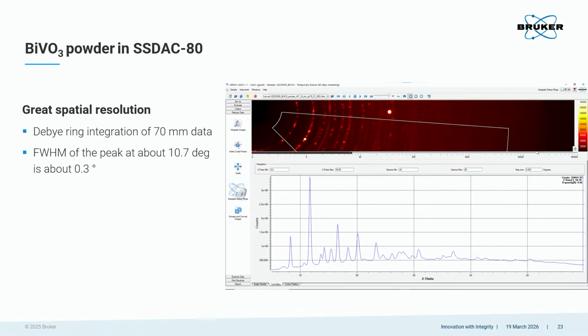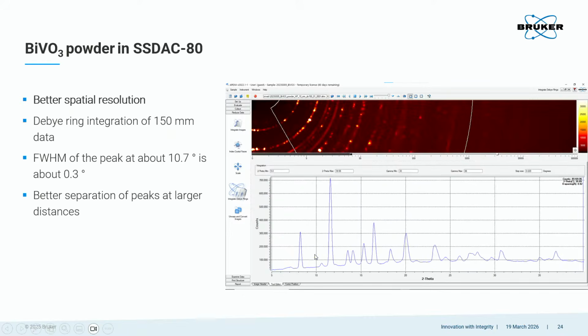Yep. So here is what I want to show you. They were looking at the spatial resolution, and the diffractogram almost looks like it's background corrected. This is the diffractogram from the 70 millimeter data, and what we were interested in is this double peak here. The question is, if you move the detector to 150, is the divergence good enough? Is the detector point spread function good enough? Can we resolve that? Of course it is, or I wouldn't show the slide. So here it's at 150. Oh, wow. It's nicely resolved, customer's happy.